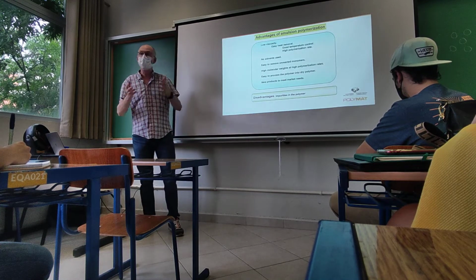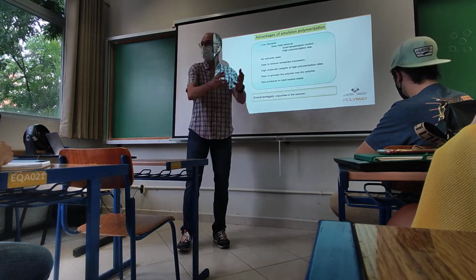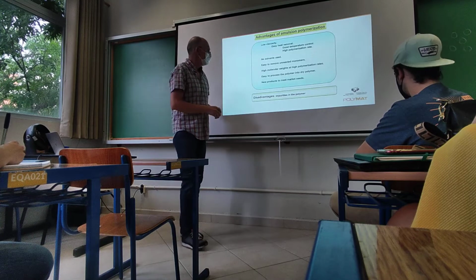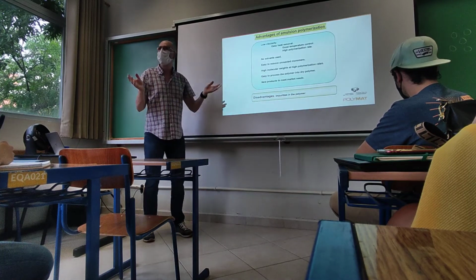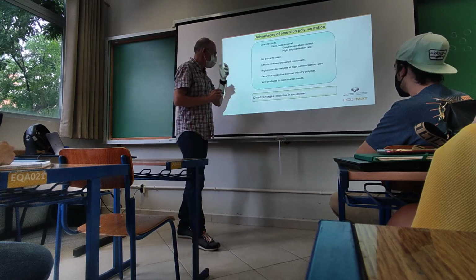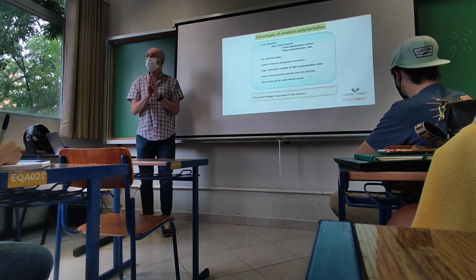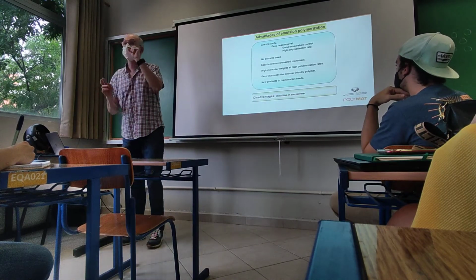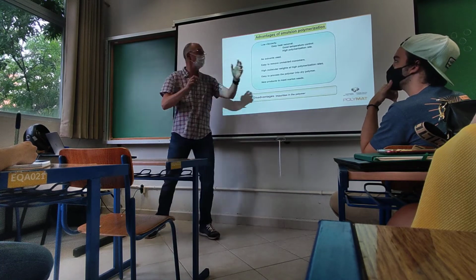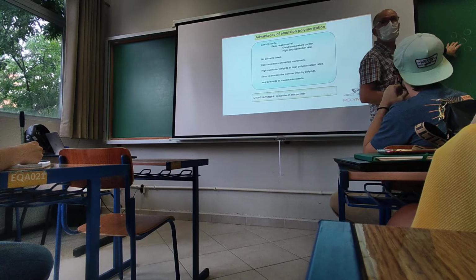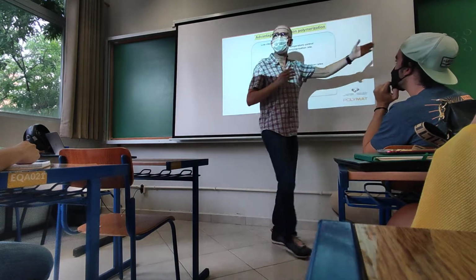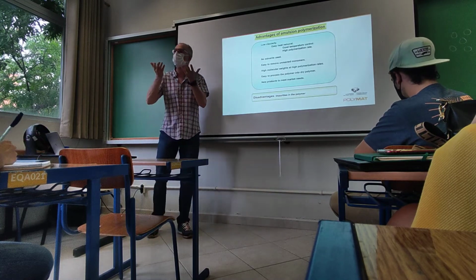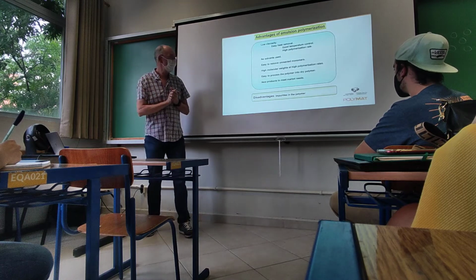So it's easy to make emulsion polymers. The dispersion can be used, as I will show you now, in the way they are produced, as a liquid, or they can be coagulated and used dry. Okay? And the possibility of polymers is immense. The main disadvantage with respect to other techniques is that we have impurities in the polymer. As you will see, we have to use surfactants or emulsifiers to stabilize this colloidal dispersion. Okay? So stabilizing this requires surfactants. Surfactants are a problem once you produce the film, because they migrate to the surface and make the polymer more hydrophilic.